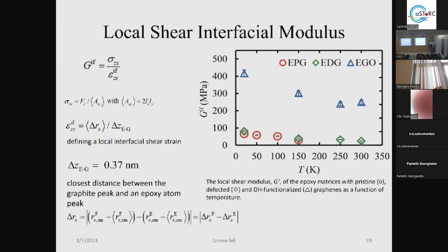It depicts, let's say, the adhesiveness of the interface between the epoxy and the graphene interface. And we calculate this for different temperatures and for the 3 different systems. We can see that the EGO, the epoxy graphene oxide, wins on this plot as it has better adhesiveness. And the reason is because of the brushes, let's say, of the graphene oxide,